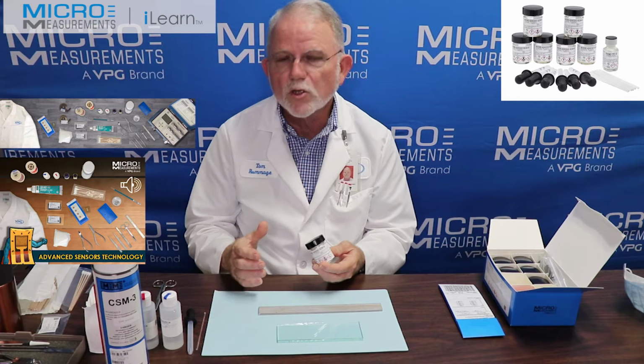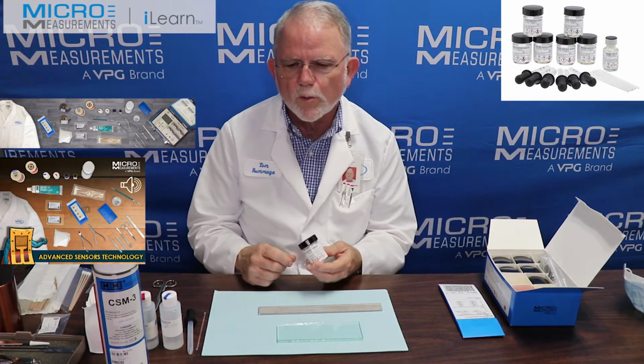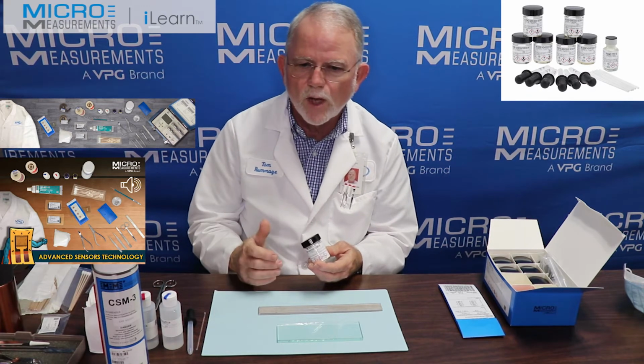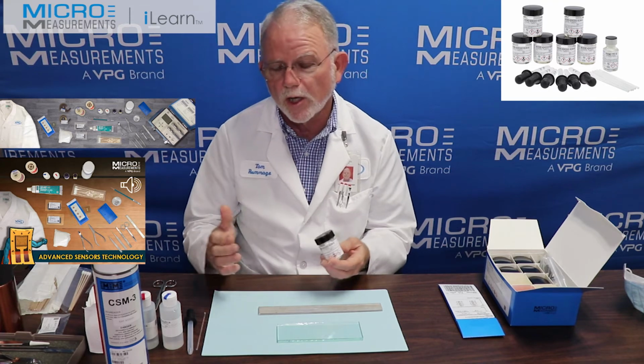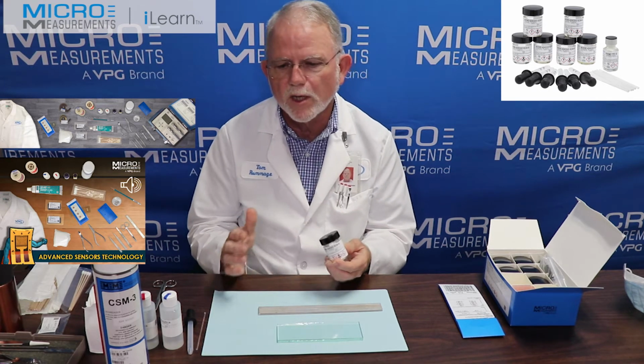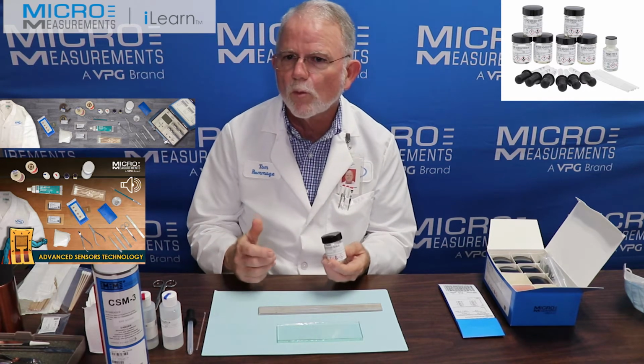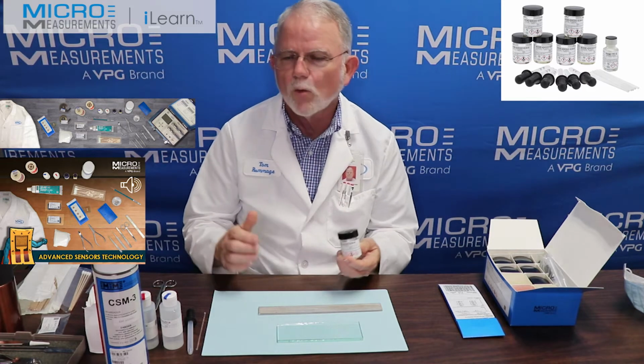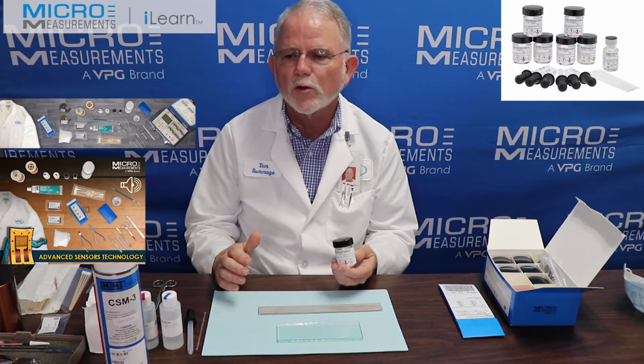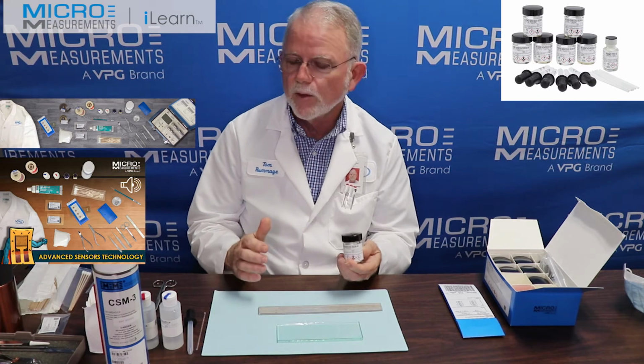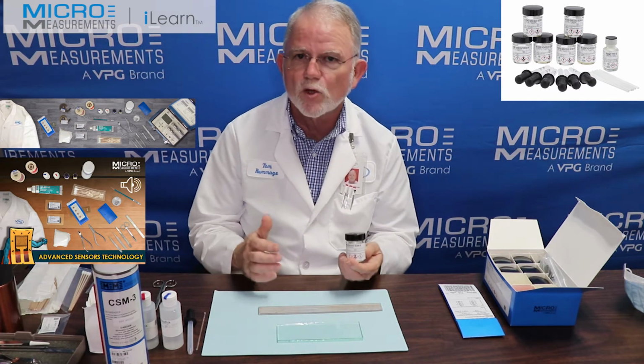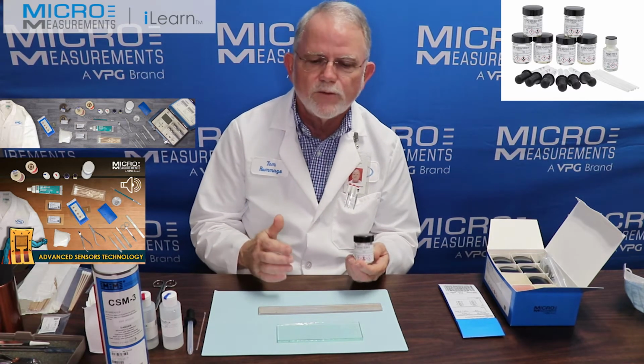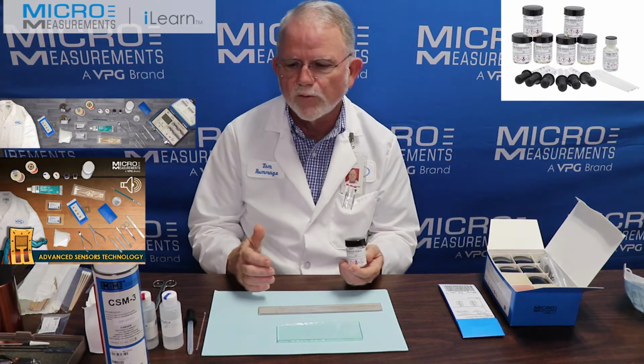The one exception is creep. We lose a little bit of creep performance at the top end. So if you're building a high precision transducer and you're going to go to 400 degrees Fahrenheit, this might not be the best adhesive for you. But for general purpose stress analysis work, it works perfectly all the way up to 400 degrees Fahrenheit. And the magic thing about that is the AE-10 cures at room temperature. AE-15 can cure at 125 degrees Fahrenheit.